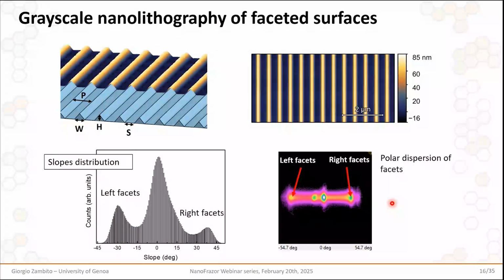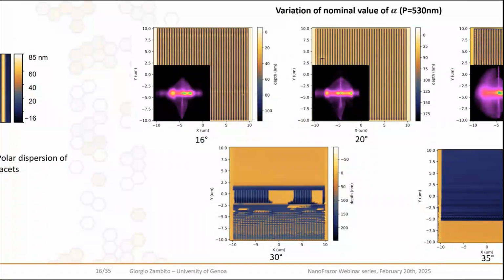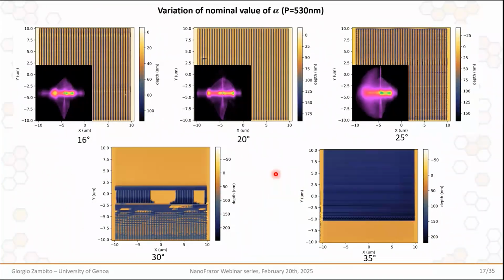So given this capability to perform lithography of faceted nanopatterns, we started playing with the geometry parameters that the geometry we are trying to pattern consists of. Basically, we observed that, for example, for alpha tilting, where alpha is the tilting of the facets, for alpha values up to 20 or so degrees, we have reliable patterning of the PPA layers, while for higher degrees, we start having feedback problems and issues, until complete feedback divergence for 30 and above degrees. And this is valid for fixed values of periodicities.